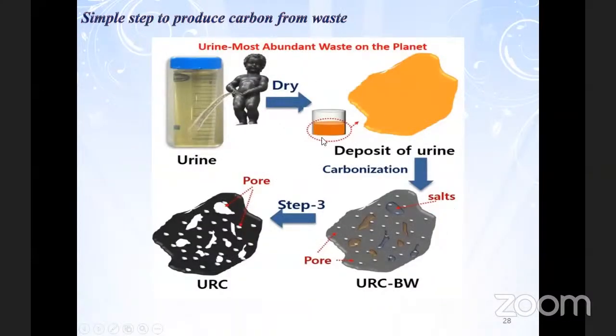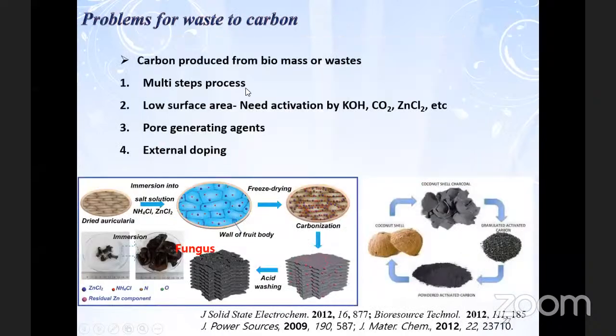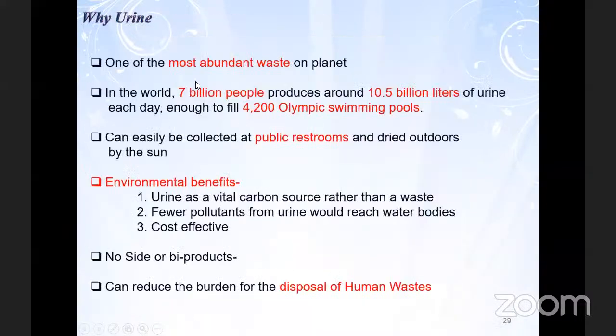What we did, we collected urine, we just simply allowed it to dry, carbonized it, and washed it, and we use the carbon. We don't need multiple steps, you don't need the activation at higher temperature, you don't need addition of pore generating agents to make it high surface area, and also no external doping was needed.